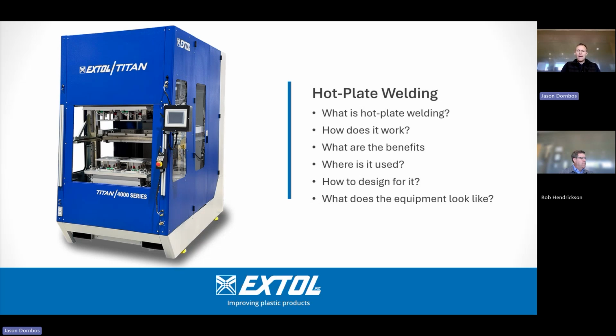Okay, Jason. So I guess, Mike, if you could explain a little bit more for me. I believe the structural foam typically has still some more dense material on the edges. Is that correct? Would you be able to get a sacrificial rib molded into something like that? If so, if you can get a sacrificial rib onto that top surface, then hot plate welding should be doable. But once you get to the more porous part of the foam area, the amount of plastic that we have available for welding, you'd really probably struggle to get any kind of strength out of it.